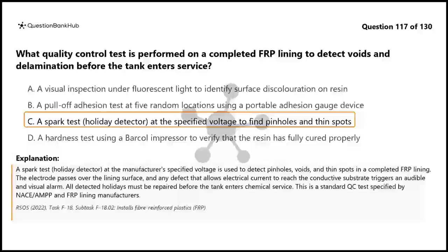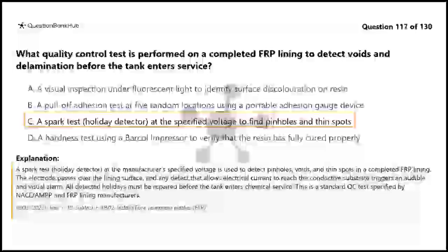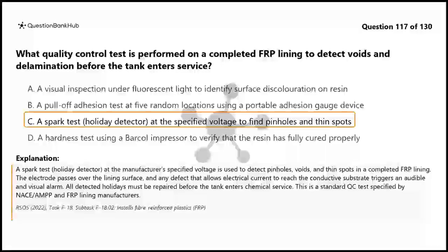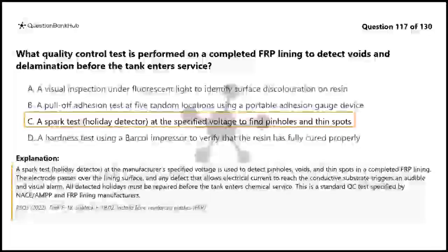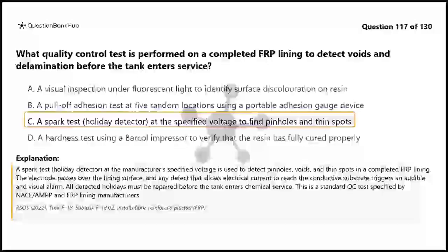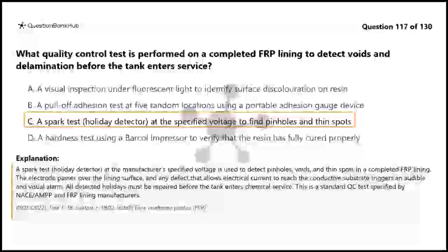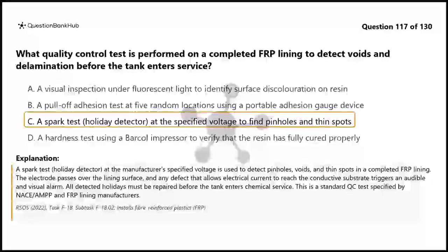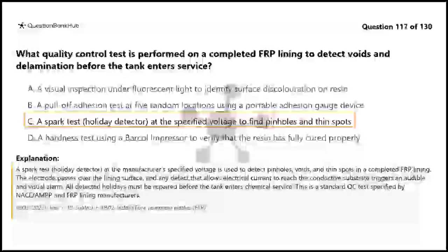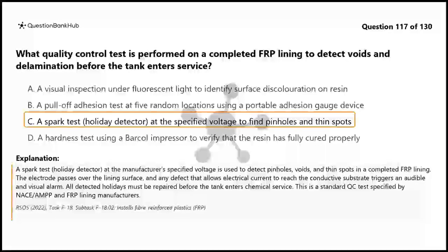A spark test, holiday detector, at the manufacturer's specified voltage is used to detect pinholes, voids, and thin spots in a completed FRP lining. The electrode passes over the lining surface, and any defect that allows electrical current to reach the conductive substrate triggers an audible and visual alarm. All detected holidays must be repaired before the tank enters chemical service. This is a standard QC test specified by NACE/AMPP and FRP lining manufacturers.